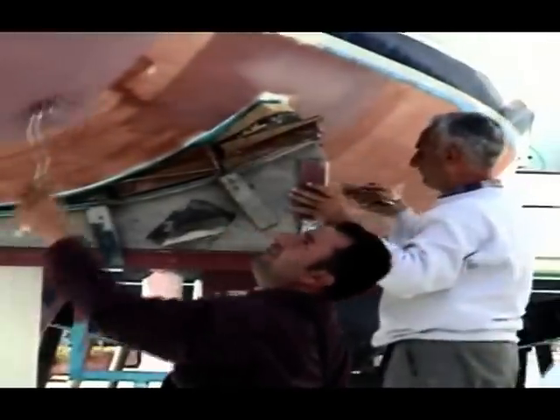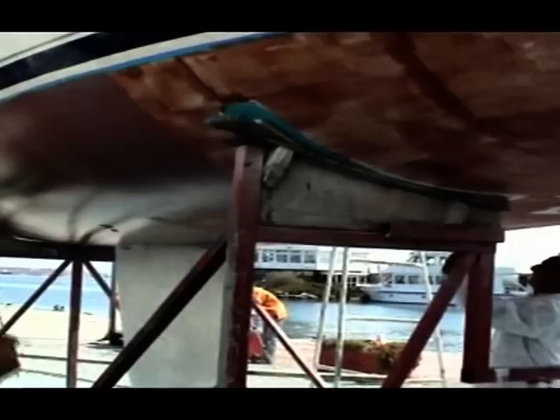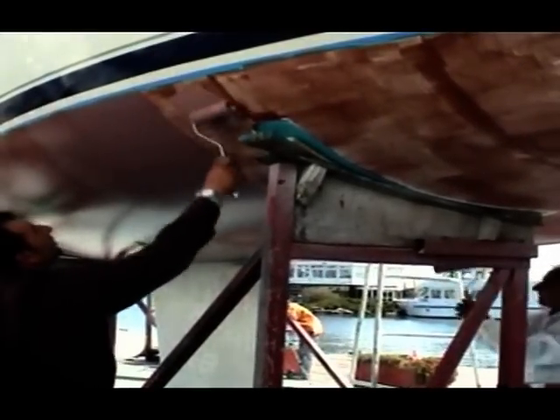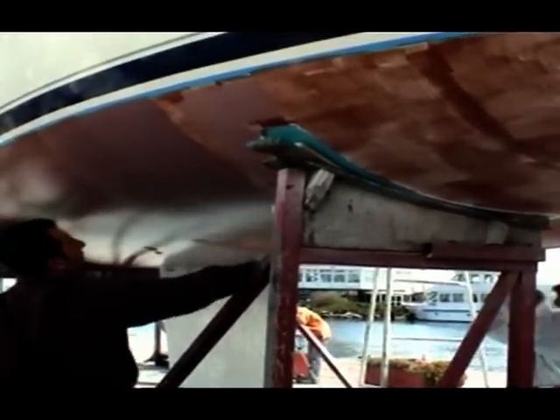As the coating cures and the moisture is driven from the resin emulsion, Coppercoat dries to a more natural copper brown colour. Consequently, it's easy to see where you're going as you pass down the hull methodically with this second coat. As with most painting, for a seamless finish, always try to keep a wetted edge.